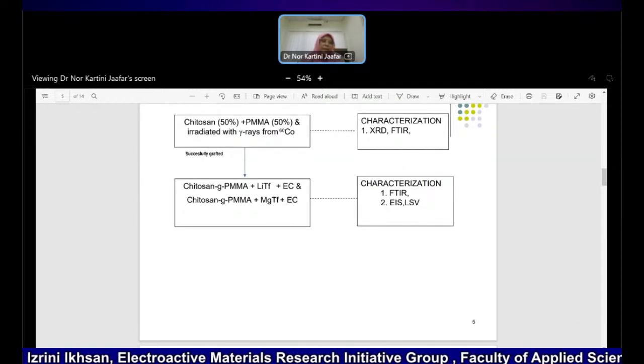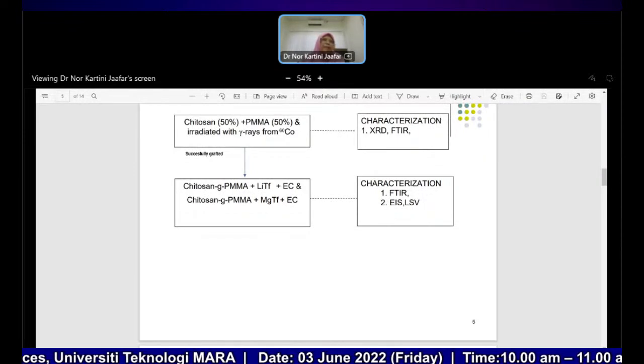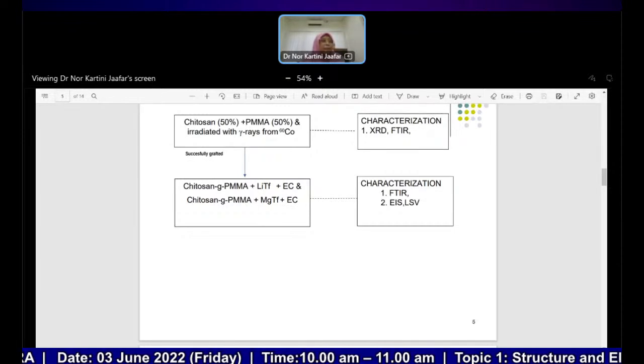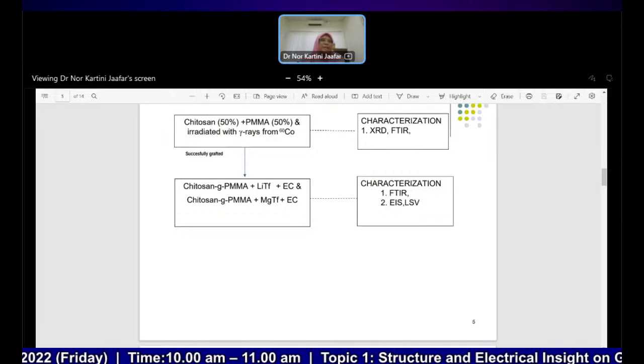First, I tried using lithium triflate. During my study, I used lithium and added a plasticizer, ethylene carbonate. The function of the plasticizer is to make the film more soft and avoid cracking. EC also helps enhance the conductivity of the film, because EC produces increased mobility of ions within the polymer matrix.